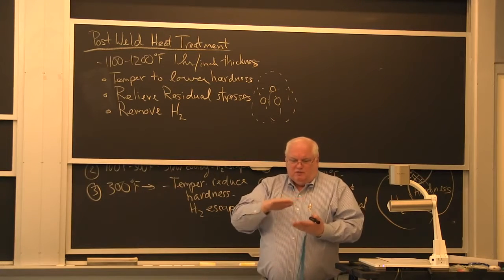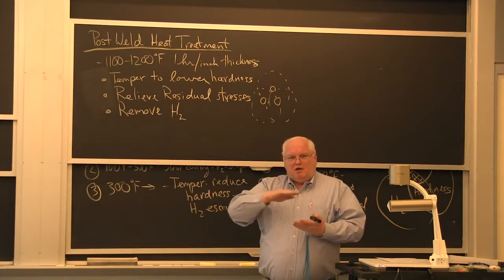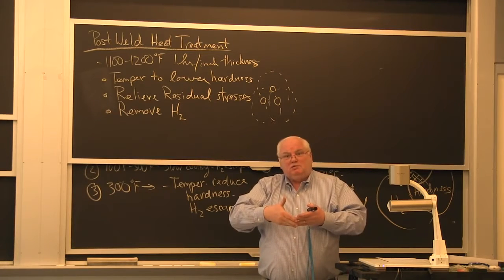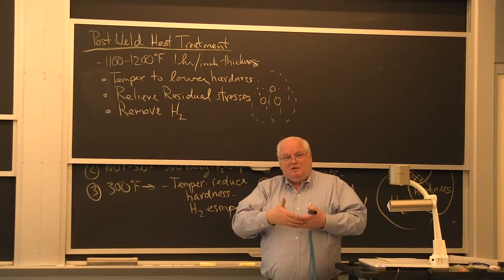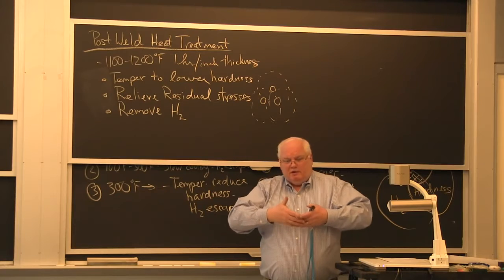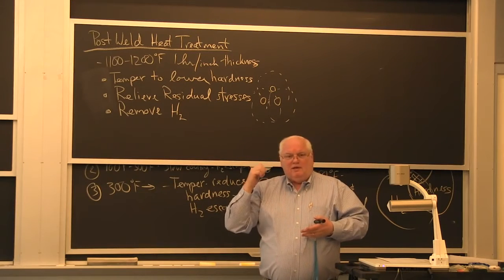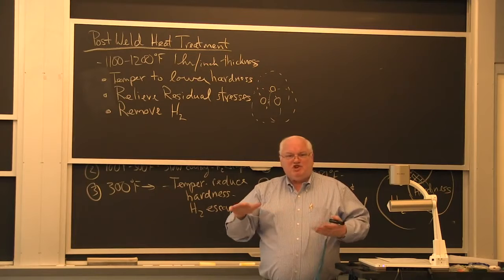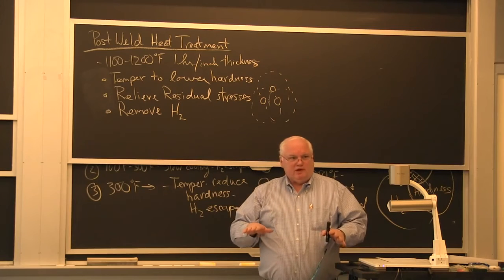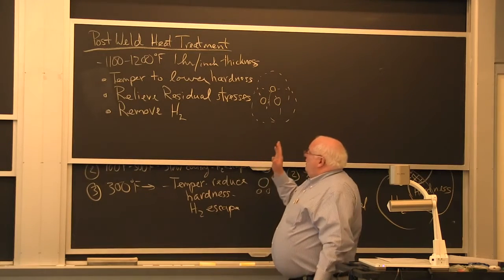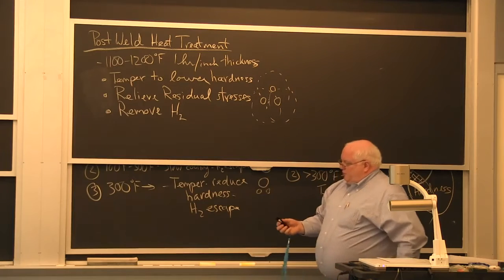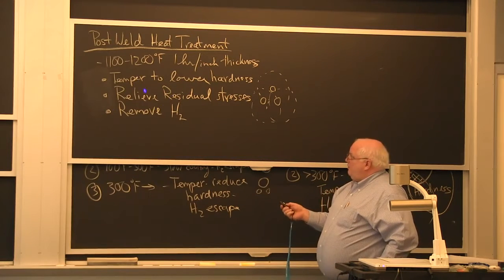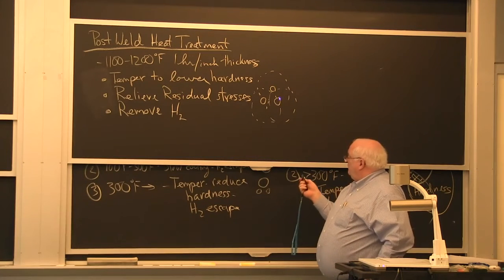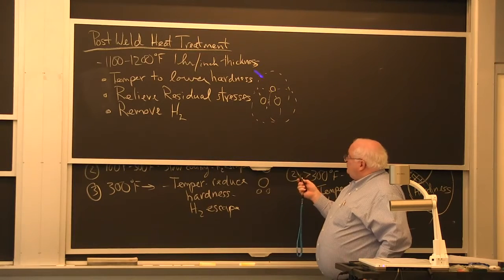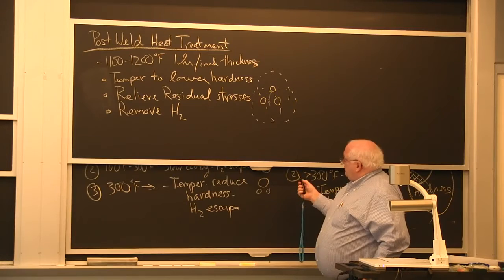So a piece of steel that, if you quenched it and cut off the top layer, it might bow up because you took off the tensile or compressive surface layer. If you put it in 1100 to 1200 degrees and then machine it, it will stay flat. Okay, it's been stress relieved. And you're also removing hydrogen big time, because when you go to 1200 degrees, the hydrogen is going to go out very rapidly. And so what you've done with the post-weld heat treatment is you've reduced all three circles.